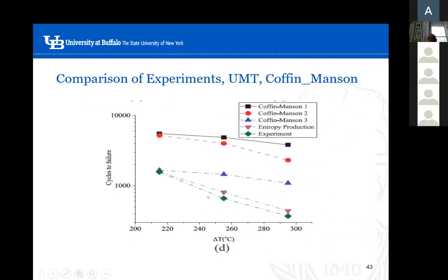Here is maybe, yeah, this is a better view. You can see the cycles to failure, delta T, differential temperature on the sample, the chip, the package. And this is the experimental data. This is what they call entropy production. And these are Coffin-Manson 1, Coffin-Manson 2, Coffin-Manson 3. As you know, there are many Coffin-Manson models in the literature. People modify Coffin-Manson equations every day. But at the end, Coffin-Manson is just a curve fit parameter you get from the experimental data.